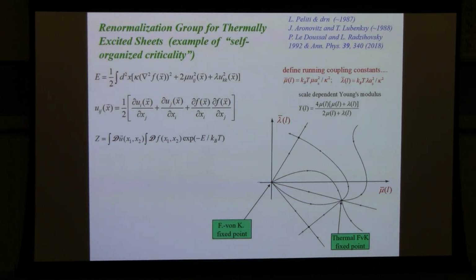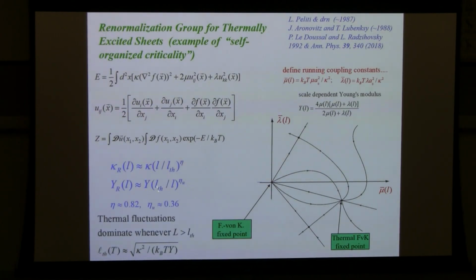And so if I go back here, you can see that this goes like L over this thermal length that you get by equating those terms. So here's the thermal length down here. What is this thermal length? Well, I'll tell you in a minute. I'll tell you now. For graphene, if you just put in graphene numbers, and I was unaware of this until Paul McEuen pointed it out, there's a bending rigidity which is fairly, this is room temperature that we're talking about here, a fairly soft bending rigidity, a very stiff Young's modulus. If you put this in, this number is about 3 angstroms.